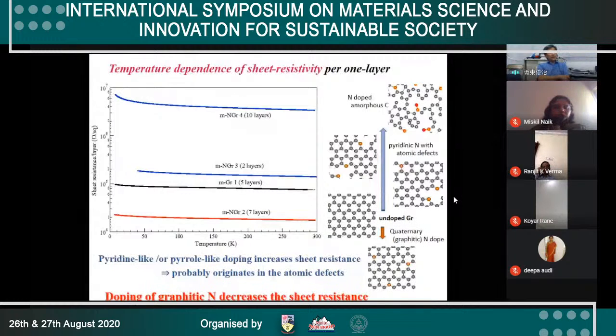When we dope the nitrogen, graphitic type doping, m-NGr2, the resistivity decreases. On the other hand, when we dope the nitrogen pyridine-like, meaning including the atomic defect, the resistivity increased a lot. m-NGr4 is like amorphous carbon, with a lot of nitrogen in the graphene network, but not uniform. So from this figure, we conclude that graphitic doping decreases the sheet resistance. Maybe the increase of the resistance is caused by atomic defects, I think.